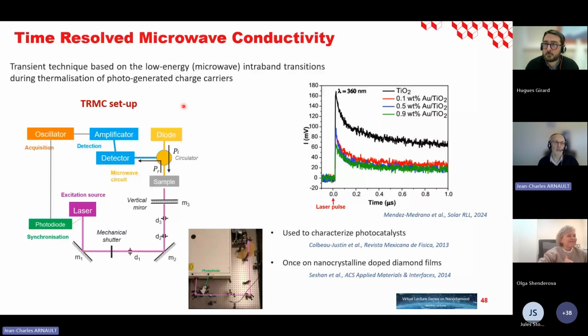Okay. So to investigate the photoactivity of this nanodiamond, we use this technique named time-resolved microwave conductivity. So what is the principle? The sample is a powder. Usually all the first results I will show concern powder just after the gas phase treatment, so oxidation or hydrogenation. This powder will be exposed to a microwave field, and at the same time, a pulsed tunable laser can illuminate the sample. Of course, if you generate charge carriers in the sample, the conductivity will change and it will affect the reflected microwaves. And this is the signal you will detect, amplify, and be able to measure.